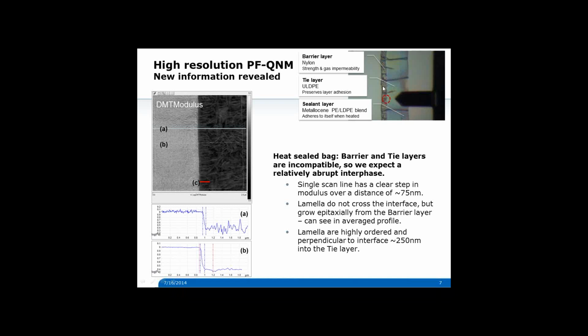And then this barrier layer here is the part that actually keeps the chips fresh, because that's what keeps the gas and the moisture out of the bag. And this tie layer is really important because it allows the layers to stay together once you've bonded everything together. Otherwise, it would delaminate. So in this image, we're looking at the modulus map of this interface between the barrier and tie layers in the heat sealable bag.